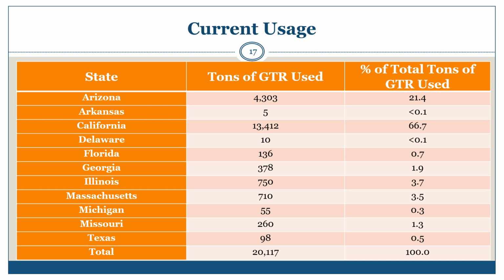The NAPA report did not include use of GTR in surface treatment such as chip seals, which is a major source of consumption. NAPA reported that approximately 59% of the total asphalt mixture tonnage using GTR was in California, which mandates widespread use of GTR in asphalt pavements. This is not a federal requirement.